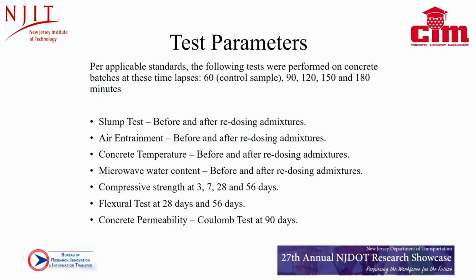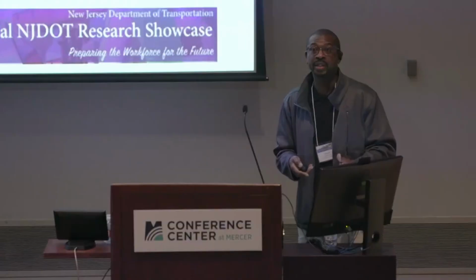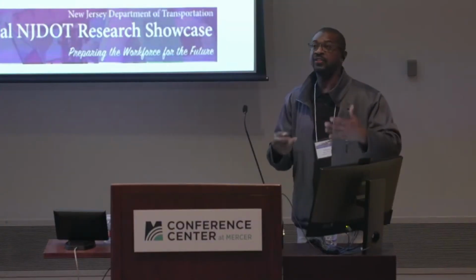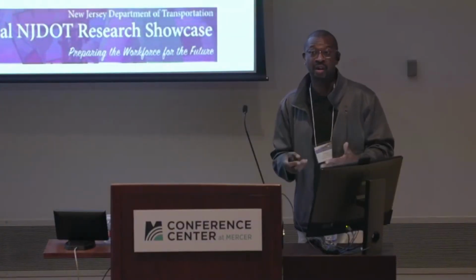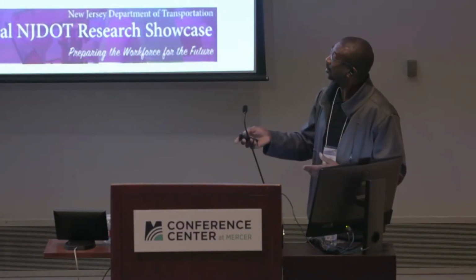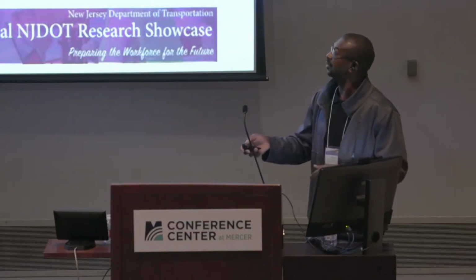We conducted pretty much all the basic tests: initial fresh concrete tests, slump tests, air entrainment, temperature, water content, etc. And of course, we made our samples to do compression and flexural tests as well as permeability tests. Because a subsequent set of research that we ended up doing off of this is the long-term effect on freeze-thaw. Yeah, I think I said it right.